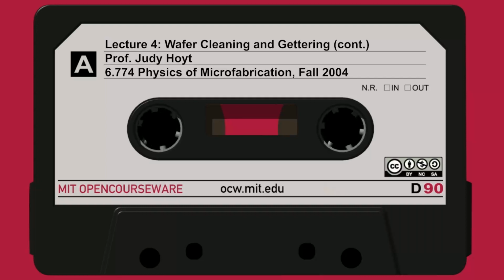So we can use that. There's a process we can use called epitaxial growth, which we're going to talk about later in this term, where we can grow material on top that's very low in oxygen. Or if you don't want to do epitaxial growth because it's fairly expensive, you can just take the wafer, and the very first step you can do is go to a very high temperature and cause the oxygen to out-diffuse, out the surface, out the front side of the wafer.